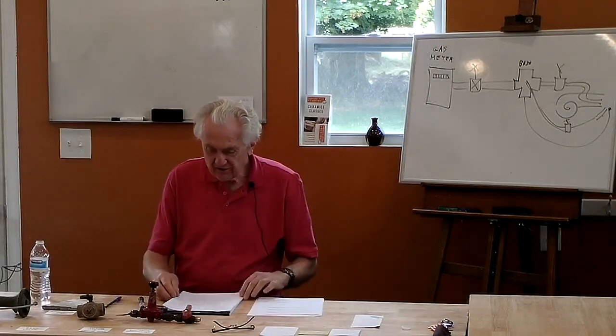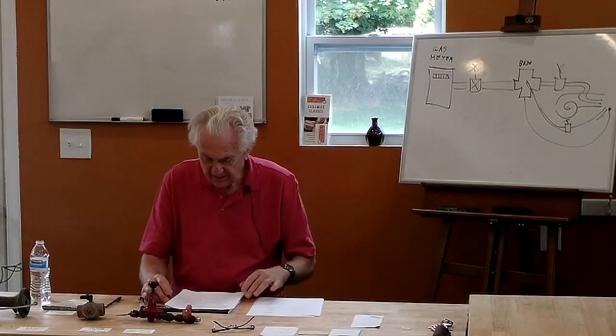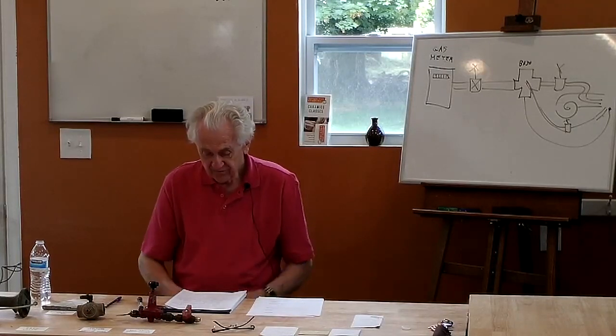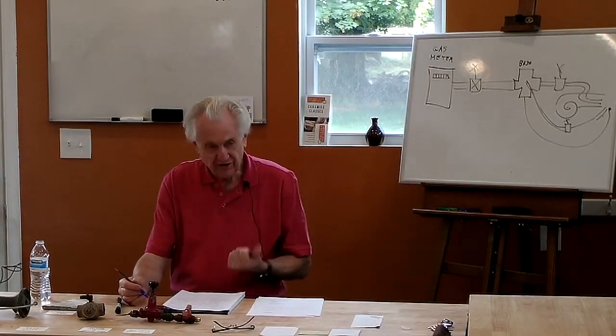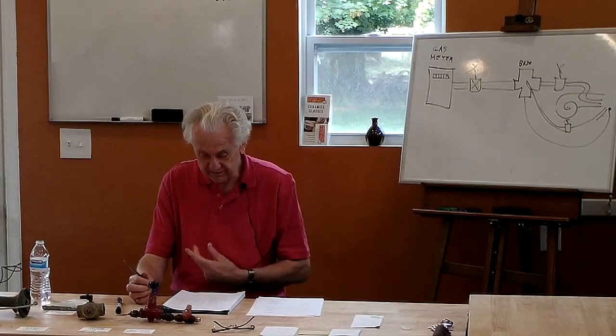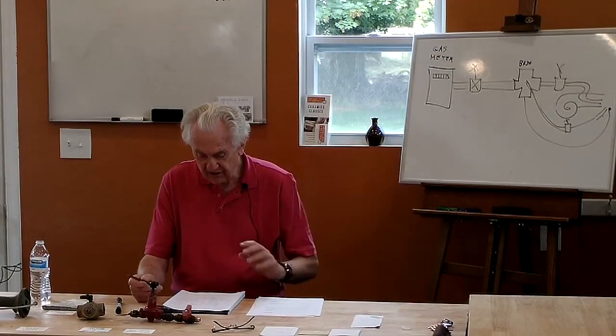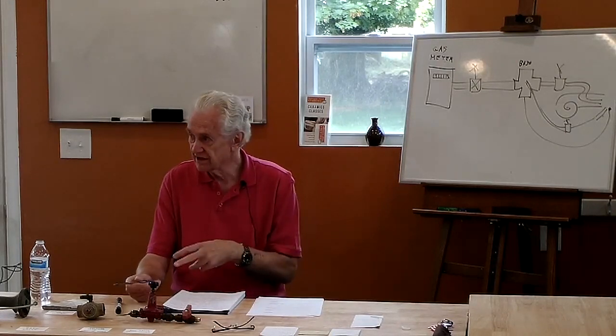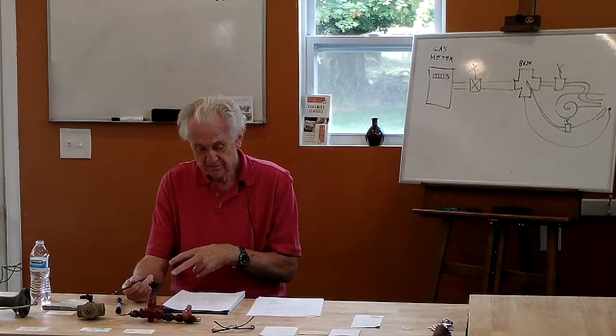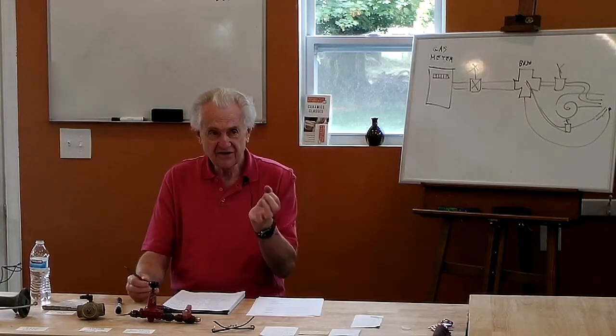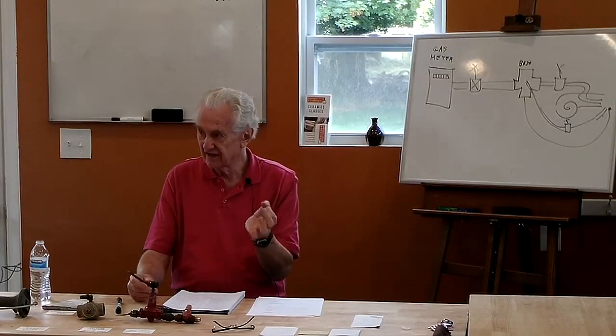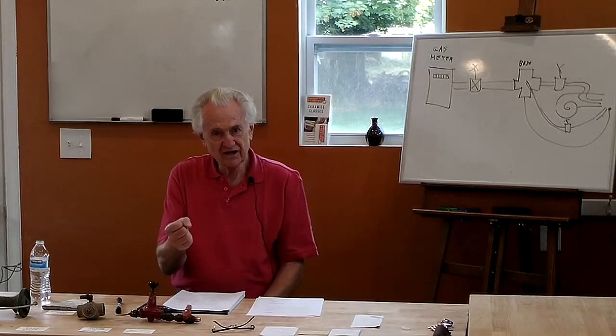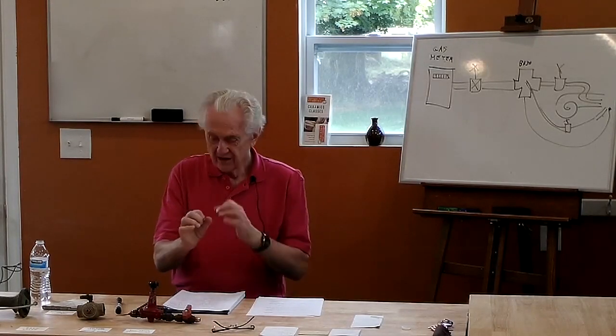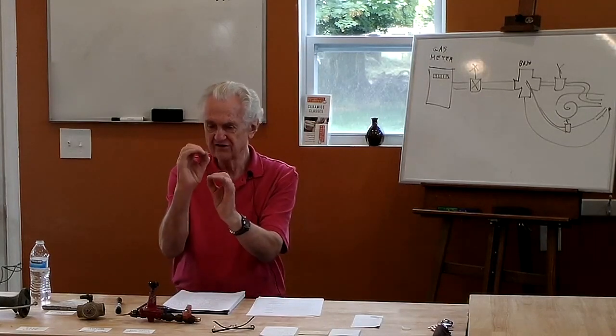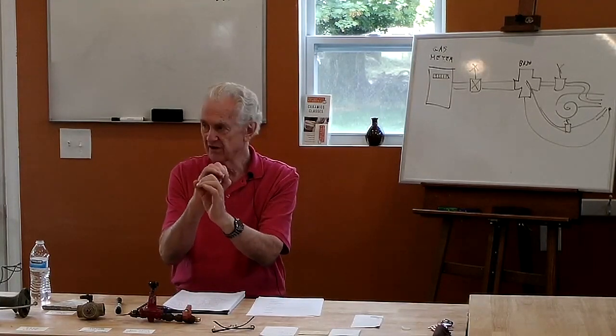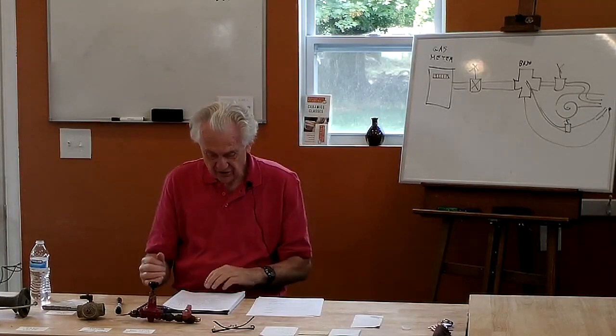So the amount of heat produced from a burner depends basically on the amount of gas being burned, and the amount of gas is determined by the pressure and the size of the opening or the size of the pipe. So heating is controlled by controlling the gas pressure with a regulator, if you have propane, and varying the gas flow, and that's the size of the opening in the pipe, generally with a ball valve. And the ball valve is nice because it gives you pretty precise control by varying the size of that opening. When the ball rotates and the two holes line up, you can get pretty precise control of the amount of gas going through.